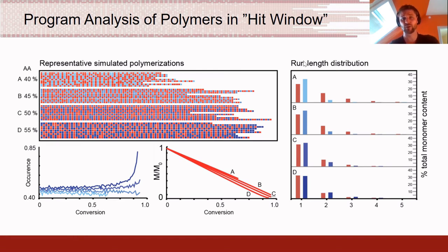To the right are the different run length distributions of all of the copolymers, and you can see that once you add in more acid, as in the blue one, the times that styrene appears in twos, as in the run length of the styrene, starts to decrease. However, the acrylic acid run length starts to increase. So the system in the simulation behaves exactly as you would expect.